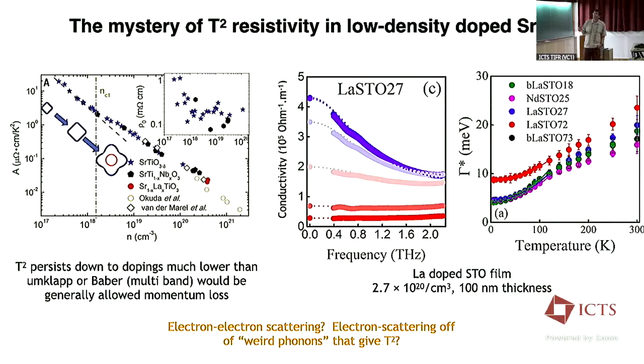One of the funny things about strontium titanate, we might call it the mystery of T-squared resistivity. Strontium titanate shows T-squared resistivity at low temperature, at low dopings, where the dopings are so small that the Fermi surface is so small that essentially the electron-electron interactions cannot be Umklapp. But yet it shows T-squared resistivity anyway. And so there is some debate about what the origin of this is.